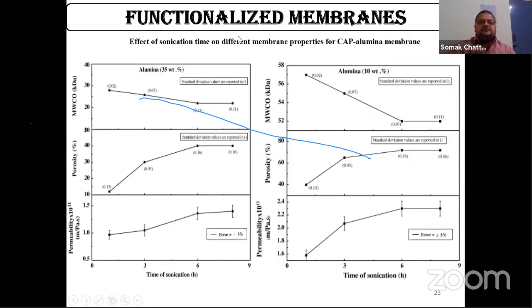There are different effects of sonication time on different membrane properties as well. The first being the molecular weight cutoff, the porosity and the permeability. So the molecular weight cutoff, when you have a proper dispersed phase of inorganics in the solution, the molecular weight cutoff will reduce. And now when the molecular weight cutoff is reduced, your pore radius will reduce. And that is also a very significant impact on the type of membrane that you are using.